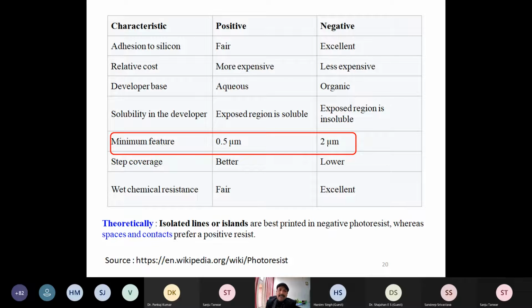You can use positive or negative, both types of photoresist, but the key parameter is what type of structure and what thickness of structure you want. In case of positive, you can get around 500 nanometer minimum feature size, while in case of negative photoresist, it is around 2 micrometer. However, in some cases people have reported much smaller feature sizes, but that requires very good quality instrumentation. Otherwise, you will not get fair edges and other things. Theoretically, if you want to make structures like isolated lines or islands, it is better to use the negative photoresist.